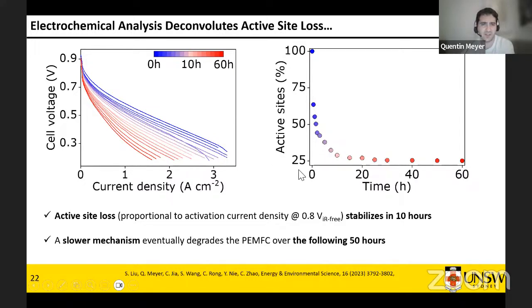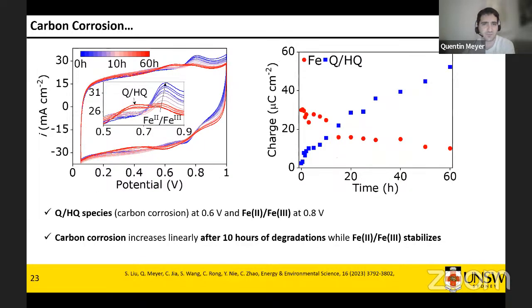And then the interesting thing is that while we don't lose active sites anymore, what actually seems to happen is we still lose about half the performance. So active sites remain, but performance keeps getting worse. So there's a slower mechanism that actually takes place, which has nothing to do with active site loss. So this is where our chemical measurements come in.